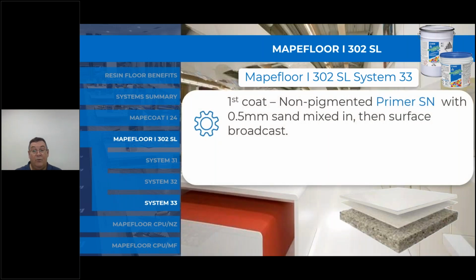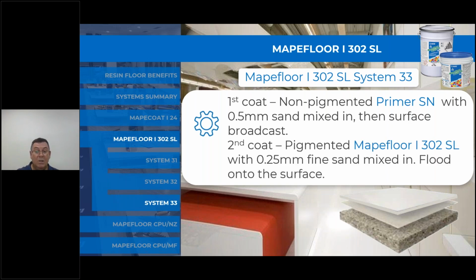So when we're looking at this I302SL System 33, the first coat is a non-pigmented primer with 0.5 sand mixed in and then surface broadcast. The second coat is a pigmented Mapefloor I302 with a much finer filling sand mixed into the resin and then flooded onto the surface, troweled across the floor and spike rolled to provide a very smooth, even and gloss finish.